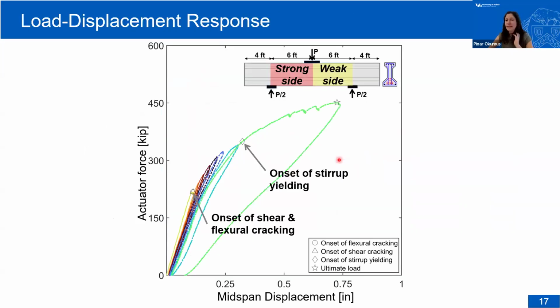And then we tested. So here's our test load and displacement response. We have the actuator force versus displacement. You can see we loaded the first cycle. At the end of the first cycle, we actually did crack the beam already in flexure and shear. We unload, and every cycle that follows, you can see that the initial stiffness is smaller. And then we had stirrups yielding, and at 450 kips, we take it as our failure load. We start seeing the plateau. We started hearing and seeing cracks falling, and we did not want things to get unstable any further, so we stopped the test here. It may have gone maybe another 20 kips or so higher, but we take this as our failure load.